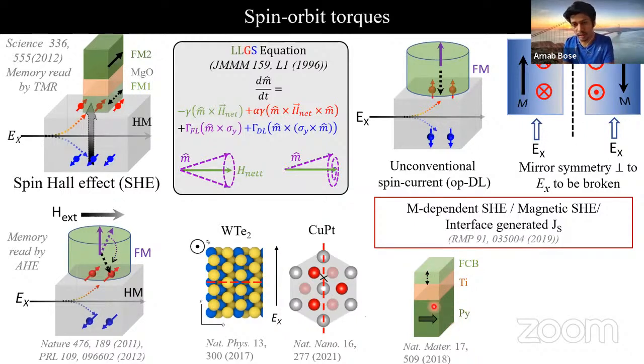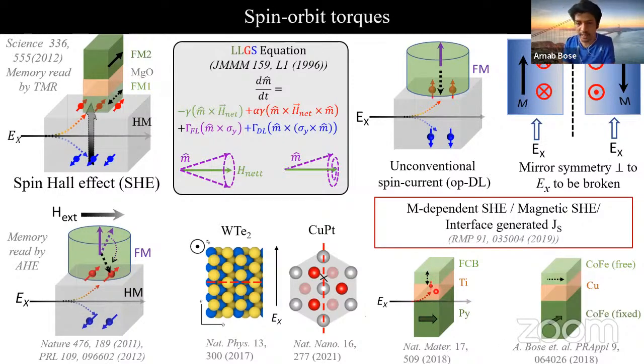In this work, it has been reported that by applying in-plane current, one can get out-of-plane spins, which will produce out-of-plane anti-damping torque. In one of my previous works, I have also studied spin torques in the in-plane GMR, where one magnet is free and another magnet was fixed. By applying in-plane current, I observed that it generates an effective out-of-plane magnetic field. So both of those are efficient to manipulate the PMA magnet.